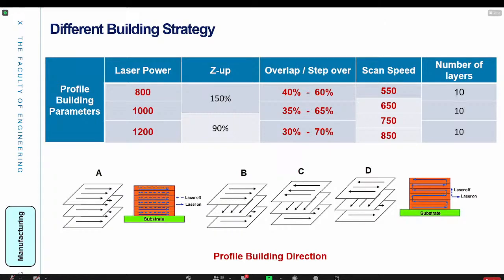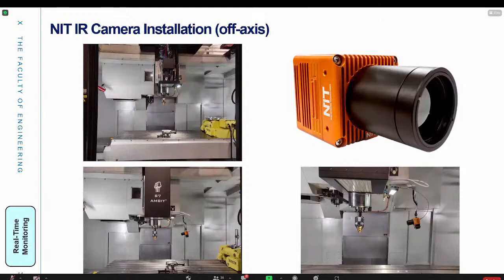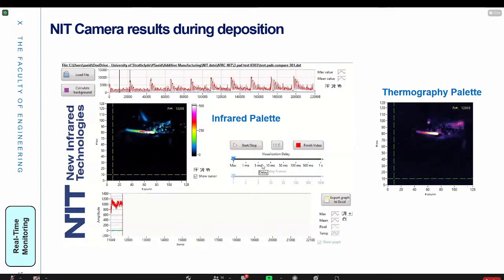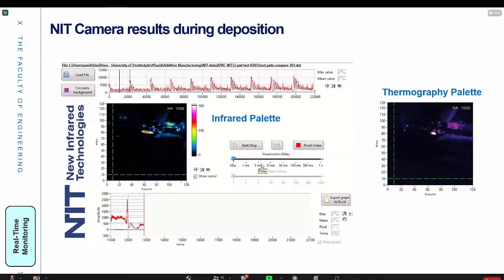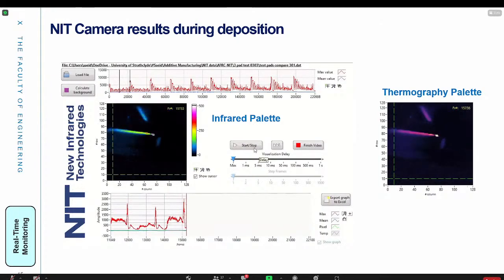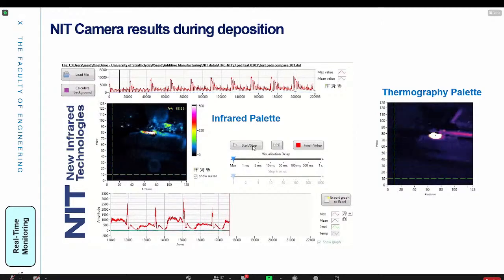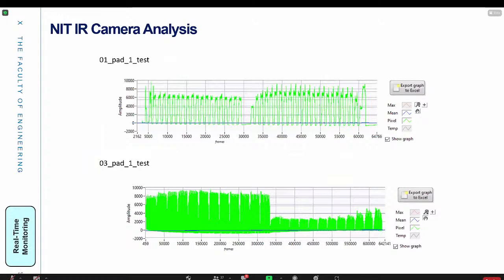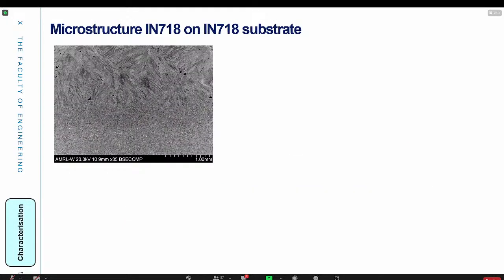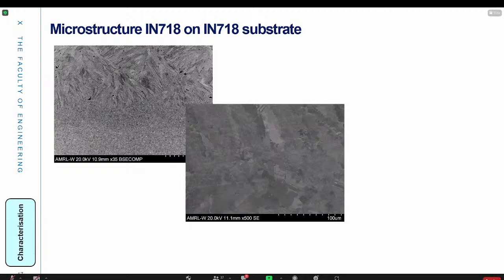We'll check for the metal parts. The interesting part here is that we use an off-axis camera installation, the infrared camera installation from NIT Europe. And the good thing about that is, as you can see, we can have control of our melt pool. And we are already in process of developing a kind of feedback control system to check the sizing during manufacturing. From the microstructure, we find that during the process, the microstructure of the material is controlled by two thermal factors, the temperature gradient and also the solidification rate.